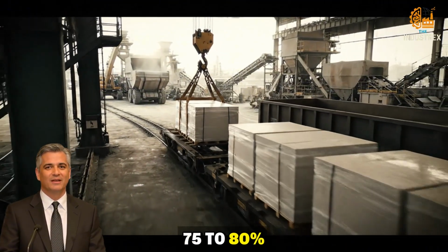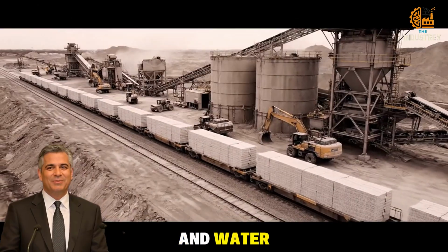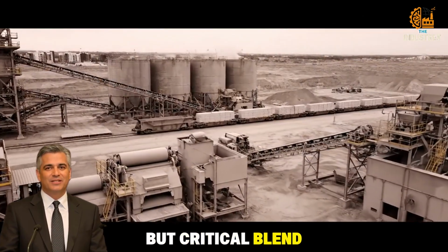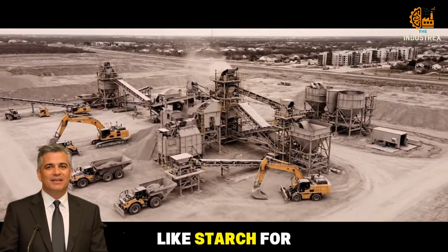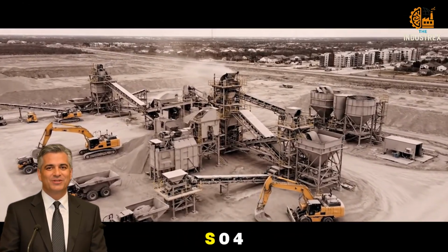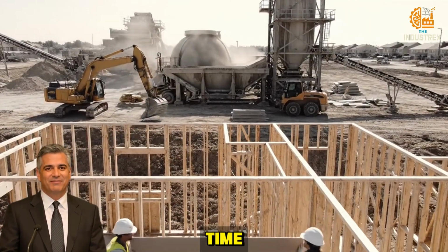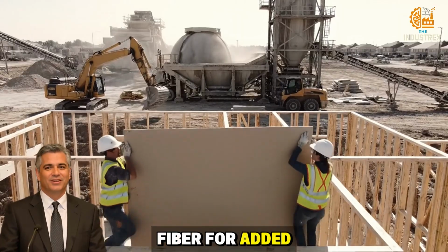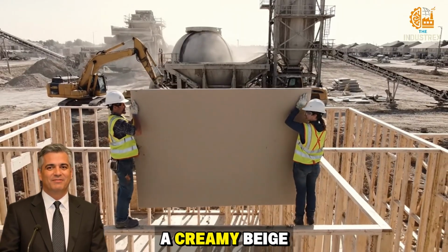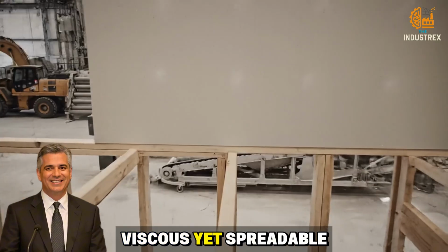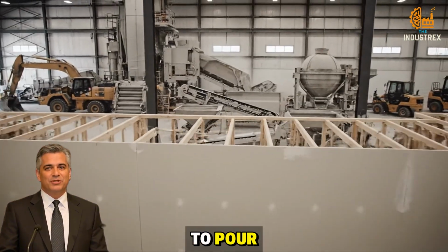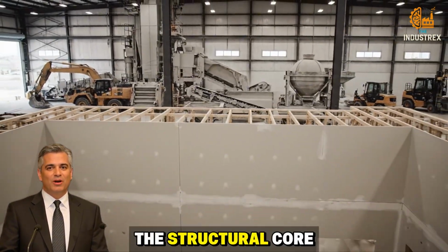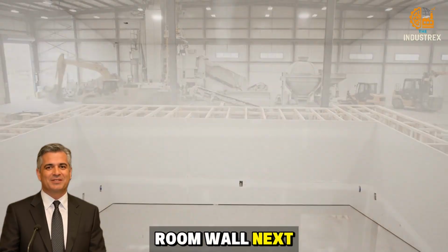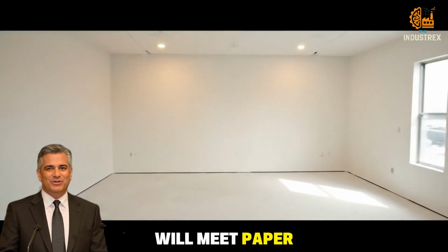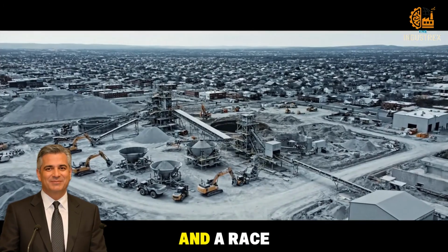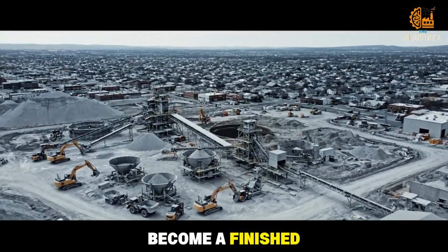75 to 80% calcined gypsum, water, and a small but critical blend of additives, like starch for bonding, K2SO4 to control set time, and sometimes glass fiber for added strength. The result is a creamy beige slurry, viscous yet spreadable, ready not just to pour, but to form the structural core of your living room wall. Next, this fluid mix will meet paper, precision rollers, and a race against time to become a finished sheet.